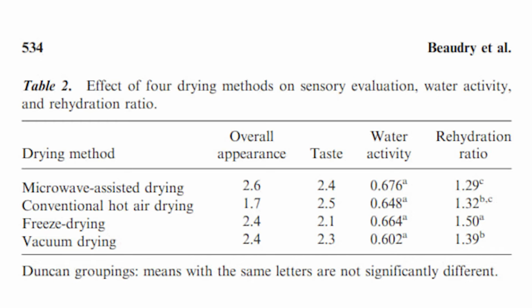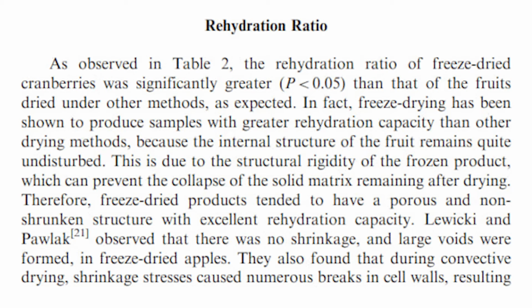As observed in Table 2, the rehydration ratio of freeze-dried cranberries was significantly greater than that of the fruits dried under other methods, as expected. In fact, freeze-drying has been shown to produce samples with greater rehydration capacity than other drying methods, because the internal structure of the fruit remains quite undisturbed. This is due to the structural rigidity of the frozen product, which can prevent the collapse of the solid matrix remaining after drying. Therefore, freeze-dried products tended to have a porous and non-shrunken structure with an excellent rehydration capacity. Lewicki and Pawlak observed that there was no shrinkage and large voids were formed in freeze-dried apples.